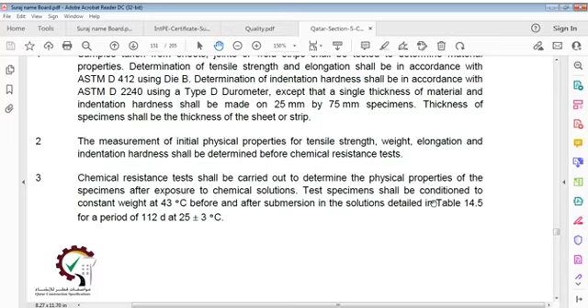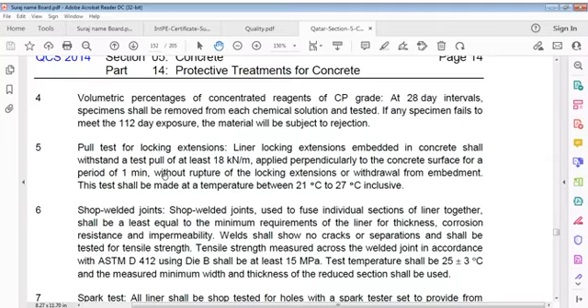Chemical resistance tests shall be carried out to determine physical properties of specimen after exposure to chemical solutions. Test specimen shall be conditioned to constant weight at 43 degrees Celsius before and after submersion in solutions as described herein for a period of 112 days. Volumetric percentages.